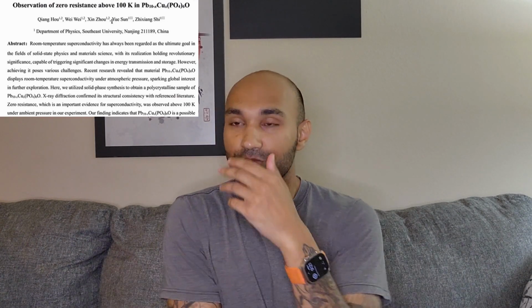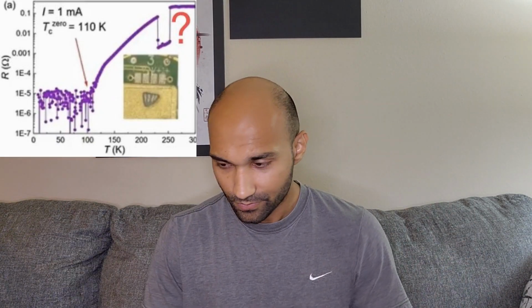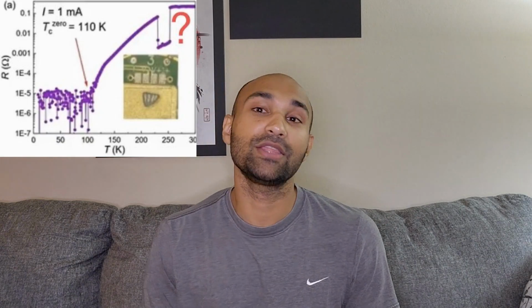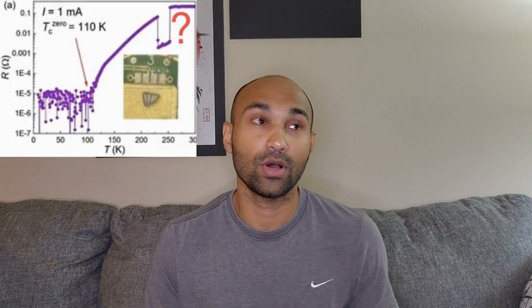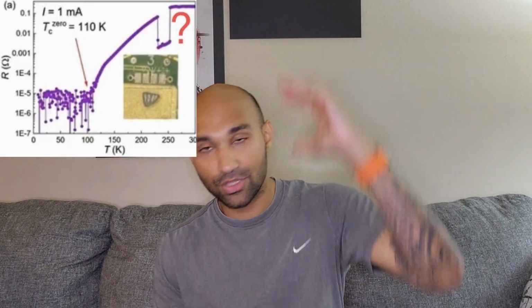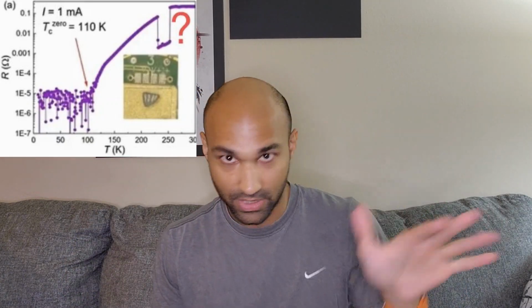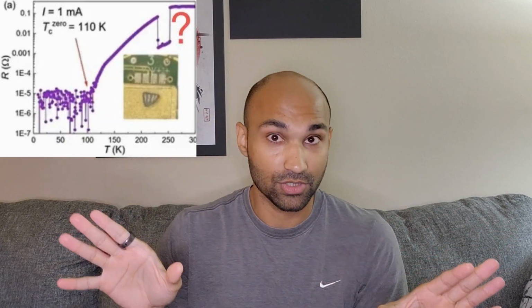This is a study that measured that the resistance of the material dropped significantly below a temperature of 110. The actual paper phrases it as above 100, which is true. But really the range that it was superconducting the most in was between 100 and 110 Kelvin. So let me be clear about that. Kelvin is 273 degrees below Celsius by definition, and zero Kelvin means zero, like no heat whatsoever. It's absolute zero.